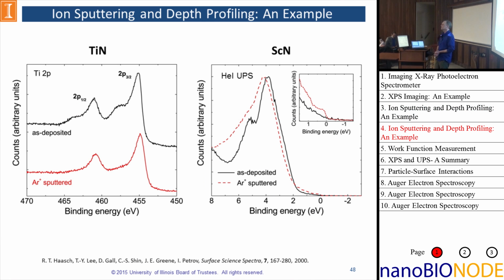Here's another example in both XPS and UPS of the effects of ion sputtering. And so this is the first order transition metal nitride, titanium nitride, that I showed you earlier in the talk. Remember we had these satellites that indicate unscreened final states. And so after sputtering, and these are conditions typical for sputter cleaning, just a few minutes, we noticed that these satellites are diminished quite a bit. And that's because we were preferentially removing nitrogen. Nitrogen's reducing to a lower oxidation state. It's actually becoming more metallic, and we're providing more screening electrons to the titanium. So you see, just by a few minutes of sputtering, we altered the electronic structure of the material quite a bit.